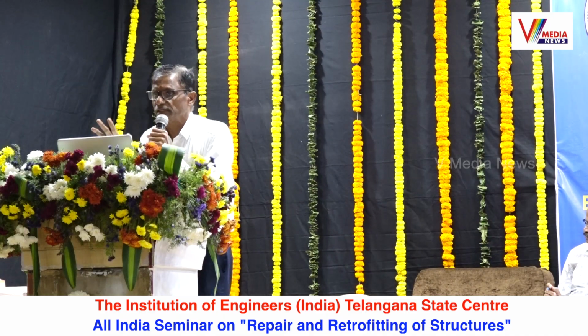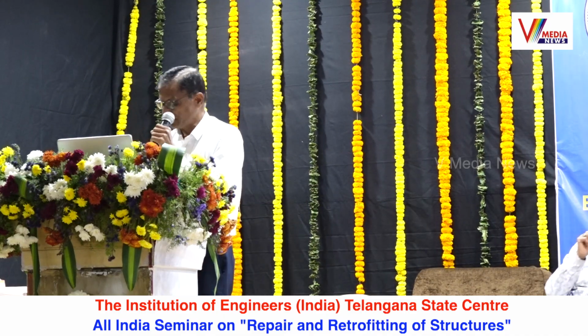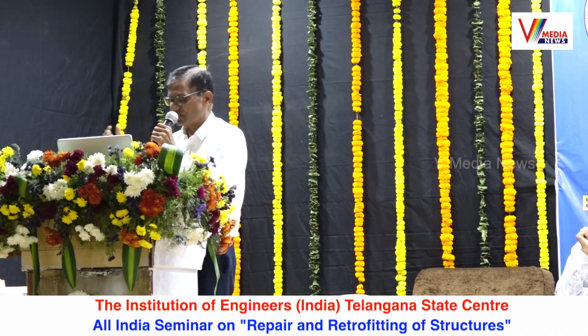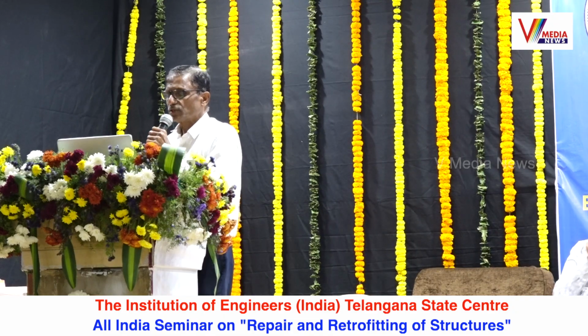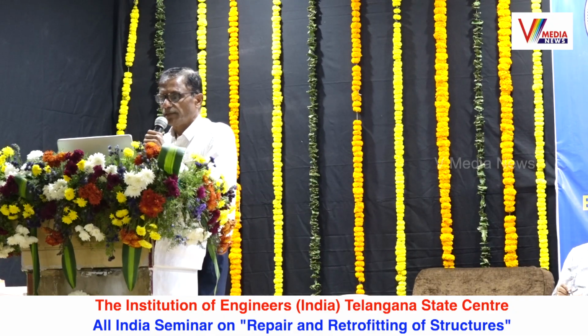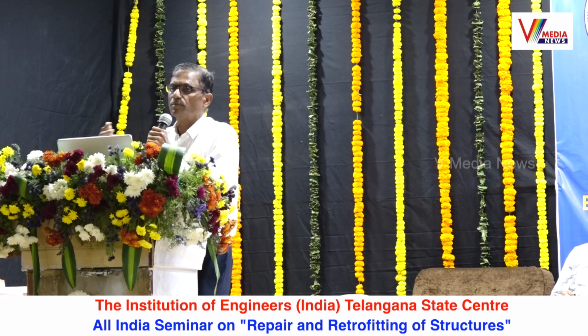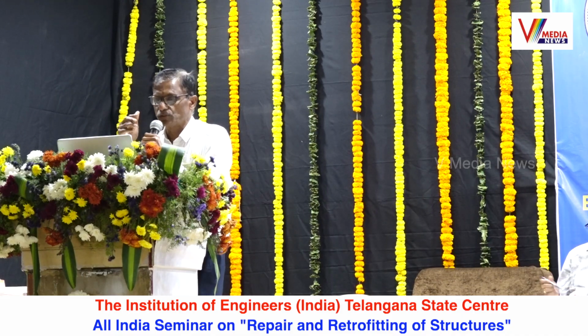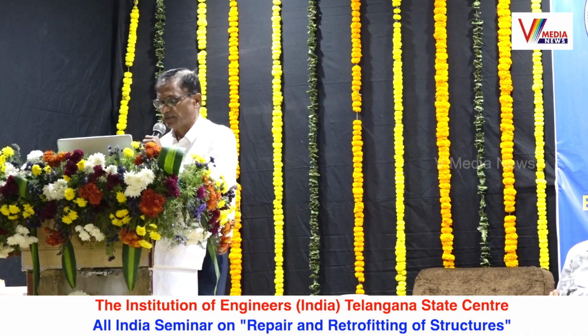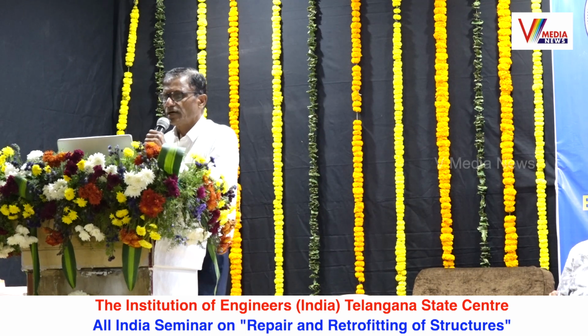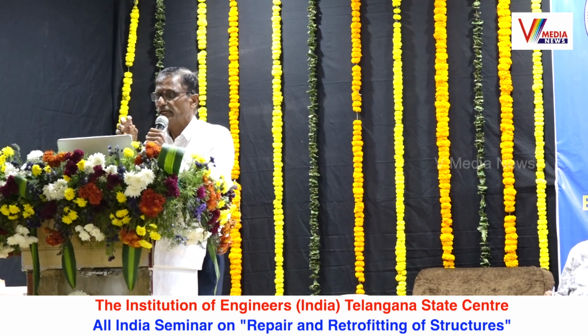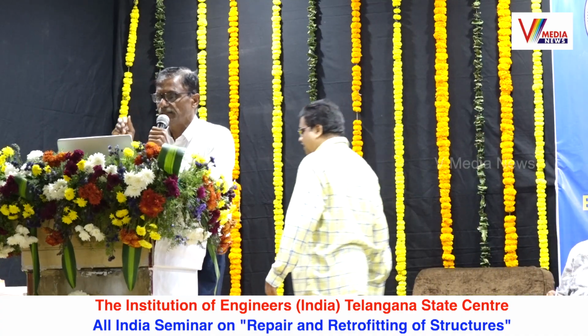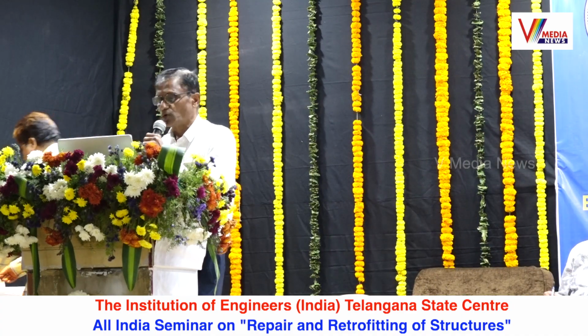How this material is useful, how it is being tested, and what kind of results it is producing. The main theme is the impact of steel fibers on durability, optimum fiber content, how much fiber content is to be used, and time dependent performance. The first test is the sorptivity test. Sorptivity measures the capillary force exerted by the mortar pore structures, which dictates the penetration rate of mortar.